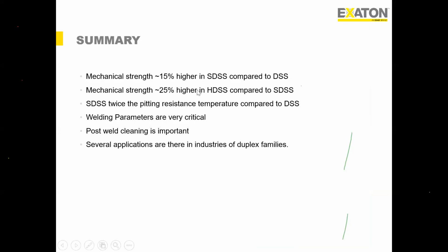So the summary is that mechanical strength for super duplex is higher, almost 15% more than standard duplex. I told you that the higher the alloying element, the higher the strength. Mechanical strength is 25% higher in hyper duplex than even super duplex. Super duplex has twice the pitting resistance temperature compared to duplex stainless steel. The welding parameters are very critical, in terms of interpass temperature and heat input, plus all the other parameters. Post weld cleaning is very important, as I mentioned, do the pickling and passivation. Try to be clean, and the welder skill is also very important.